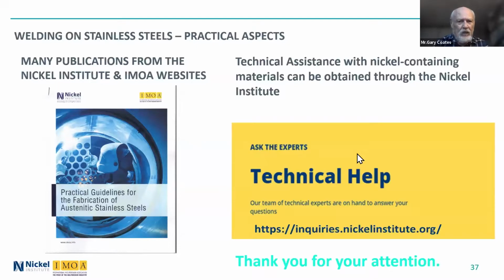Sometimes we are facing issues of fissure-like indications in liquid penetrant examinations in the junction area where the Alloy 600 weld overlay and stainless steel meet. What could be the reason and how to prevent them? Yeah. When we get into these areas where you have mixed metallurgy, an Alloy 600 overlay, there are parts of that diluted with the underlay material, which, if I understand correctly, here is 347. Although usually you do 600 on carbon steel, but it's not quite sure. The nickel chrome iron 3 electrode should be a proper one.